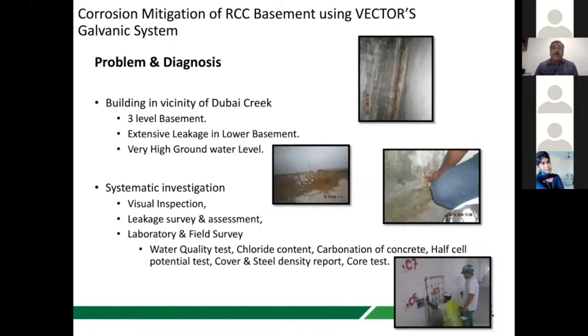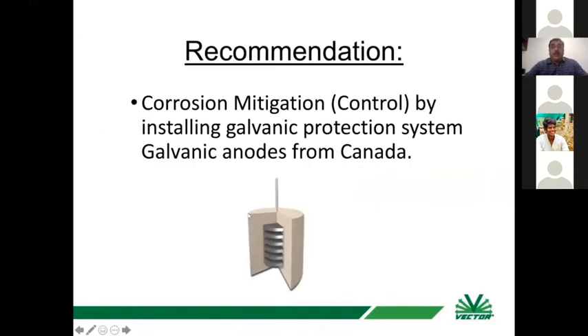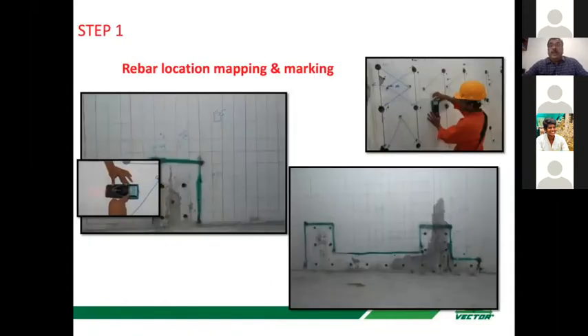So we carried out thorough NDT with all types of tests, and we even tested the quality of water, which had very high chloride content. So it was decided that CP has to be done. And we used a corrosion control system wherein the anode has a very high surface area. What we did is we marked the entire steel on the wall in the affected area so that we don't cut a single steel. So structurally, the raft and the wall are safe.